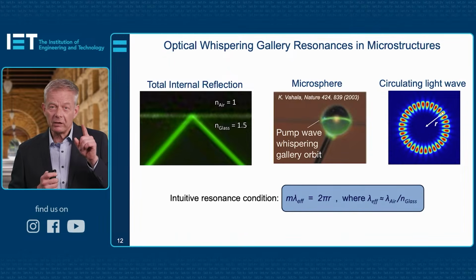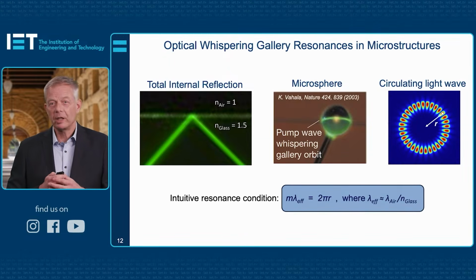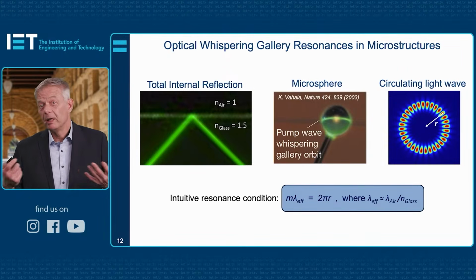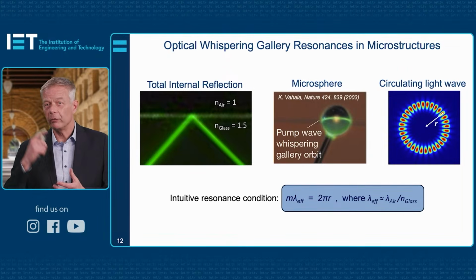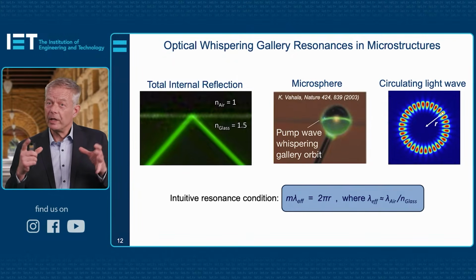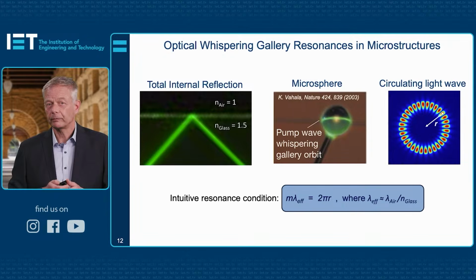It's fed by a tiny little glass fiber that you can see vaguely in the background, and then it starts circulating around the circumference. On the right you see a computer simulation of the magnetic field of this light wave that circulates around the circumference of a glass sphere with a radius r.